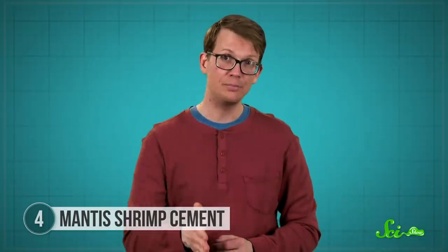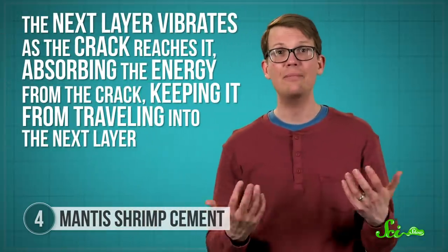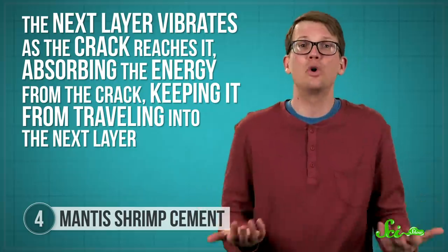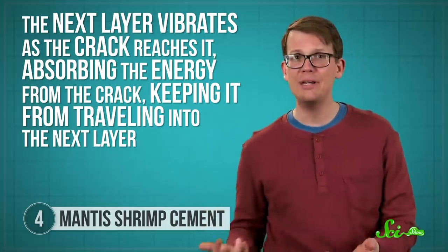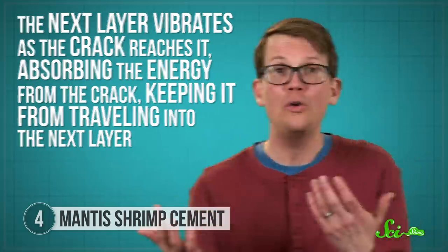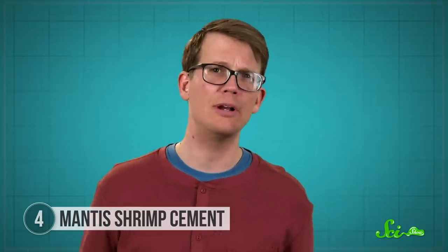If a crack does spread top to bottom, the next layer vibrates as the crack reaches it, absorbing the energy from the crack, keeping it from traveling into the next layer. Ultimately, these tiny twisting cracks stop the club from falling apart by preventing larger cracks from forming that would compromise the structure.